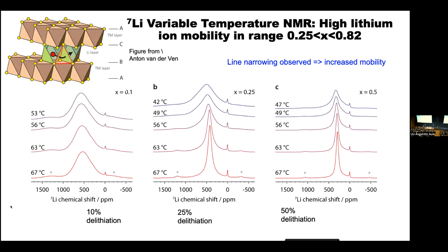And you can look at that by heating the samples up. The ions move faster, and the phenomenon gets more pronounced. So this is a classic signature of line narrowing due to mobility. And of course, the way that the lithium ions hop in between the layers of a layered structure has been well established for a number of years.